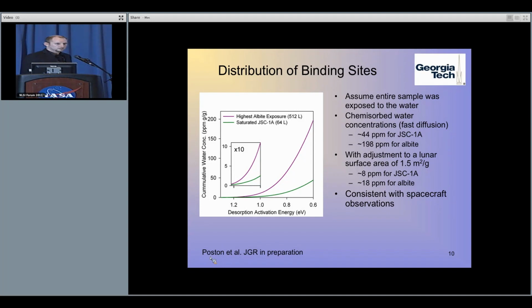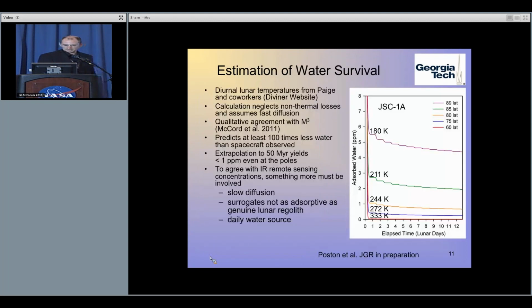The data show that the albite has about 4 times more chemisorption sites than the JSC-1A. Even if we normalize the surface areas to a common value, we still see twice as many sites on the Highlands simulant as on the Lowlands simulant. This is consistent with the spacecraft observations, at least in Science 2009, that showed more water, or more 3 micron band depth, on the Highlands than the Lowlands.